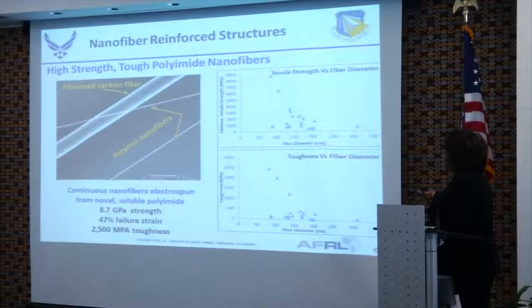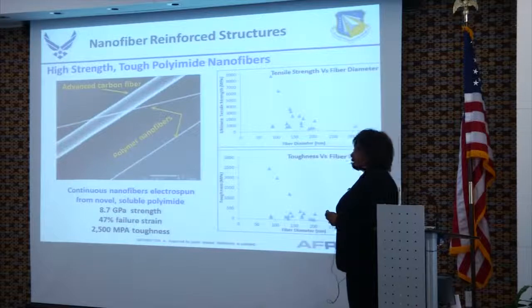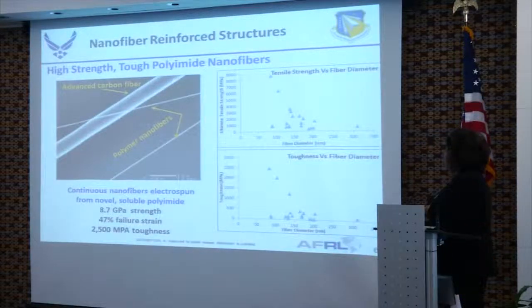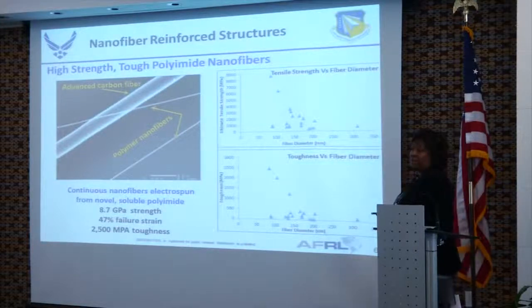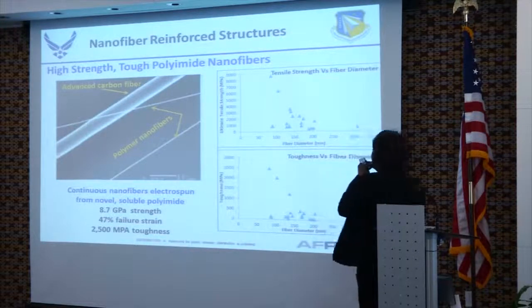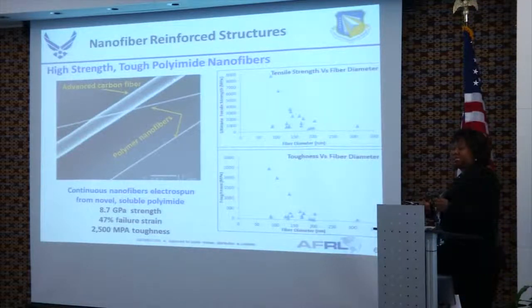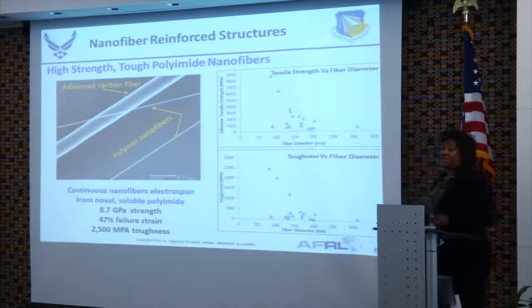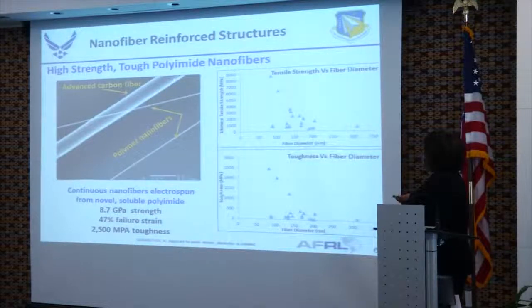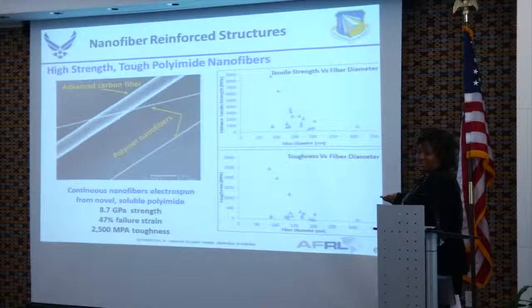To give you a point of reference, Kevlar, polyaramid Kevlar, has a tensile strength of about 3.5 to 4 gigapascals. These have a tensile strength of almost 9 gigapascals, so more than double the strength of something like a Kevlar fiber, by making these fibers really thin, with nanoscale diameters. In addition to this increasing trend in strength, as you go lower and lower in fiber diameter, you also have a dramatic increase in the toughness. So I'm told that these are the strongest, toughest nanofibers ever made.